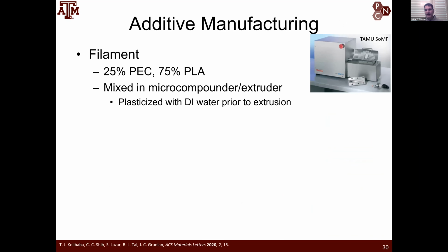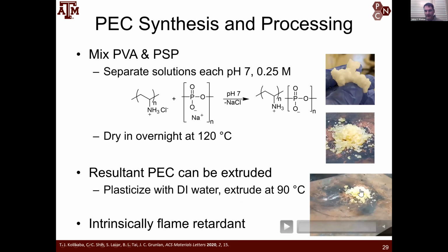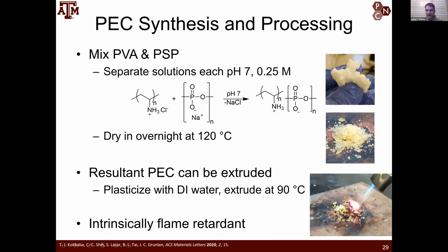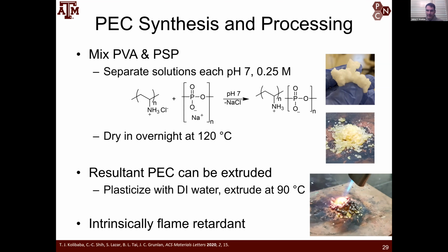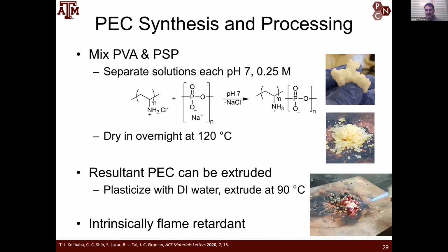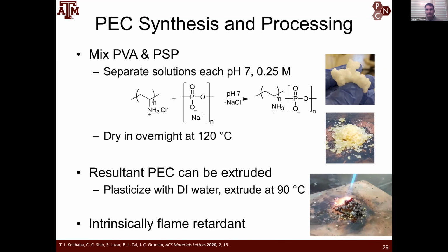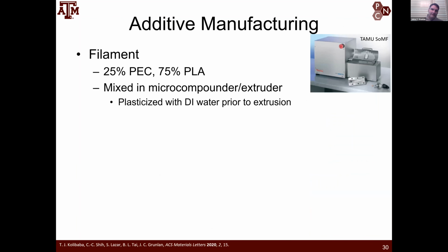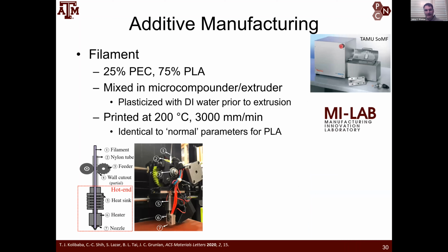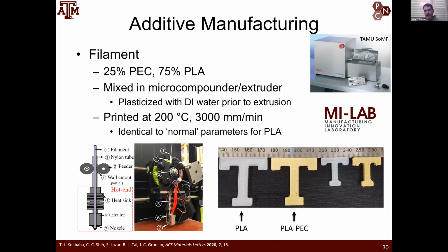first I wanted to highlight the burning of the complex itself. So that's just the powdered complex, and when you hold a torch on it, you can see that it turns black and bubbles up. So it definitely is showing you the intumescent behavior. But when we make a filament that's 75% PLA and 25% complex, it can be printed exactly the same way that the normal PLA filament is printed. And so, of course, we have to print the T of Texas A&M University here, and we're looking at the PLA-T and the T that has the 25% of polyelectrolyte complex added to it.